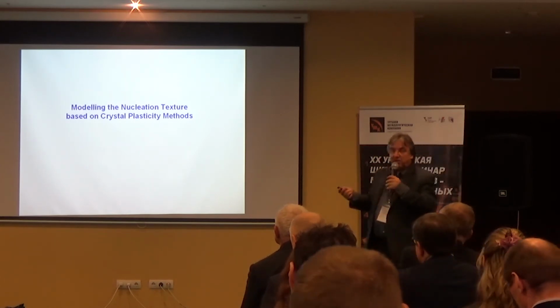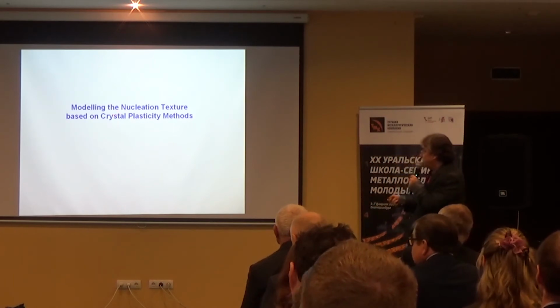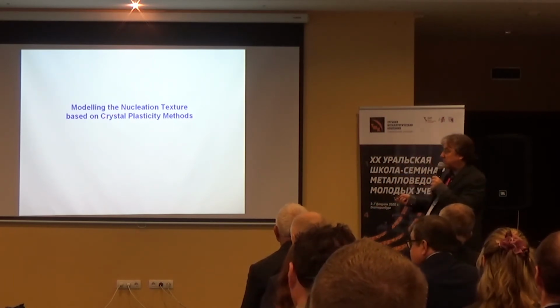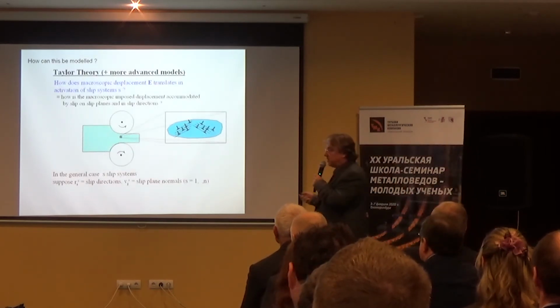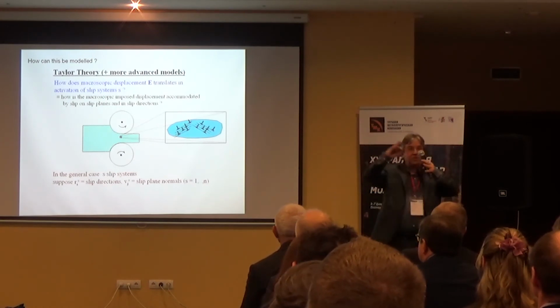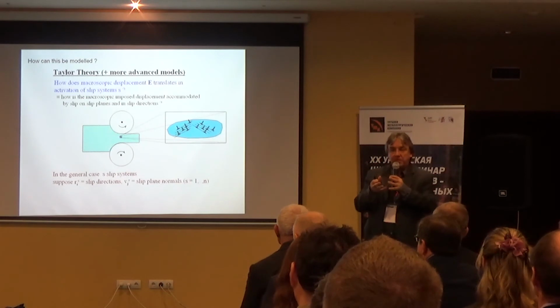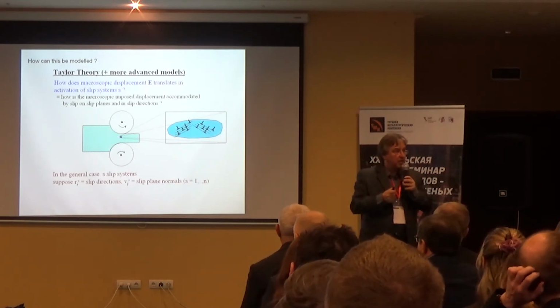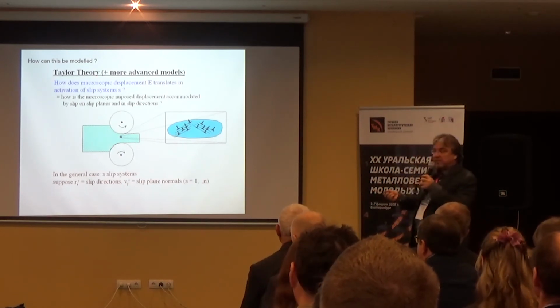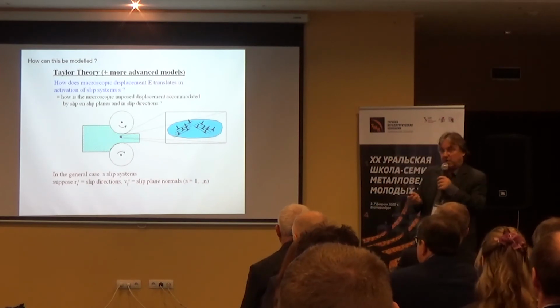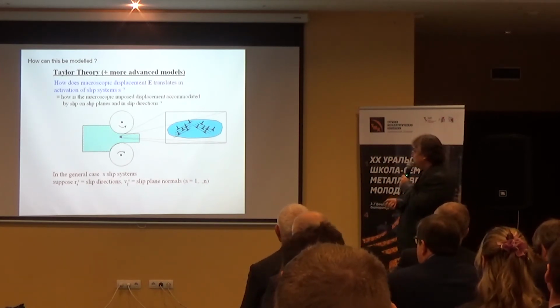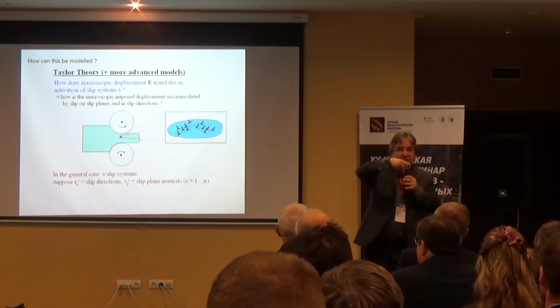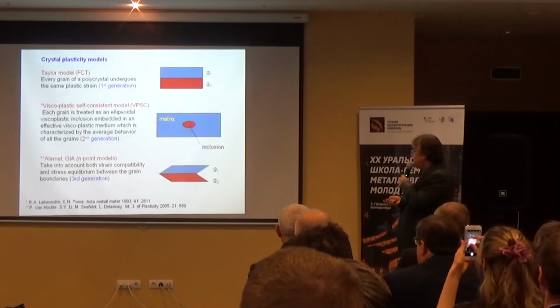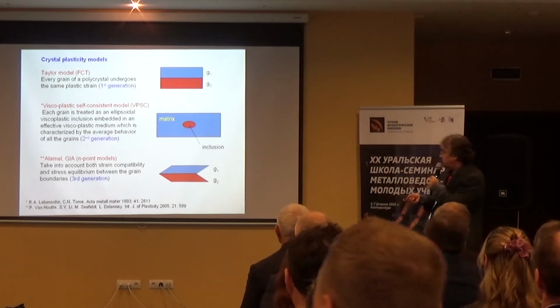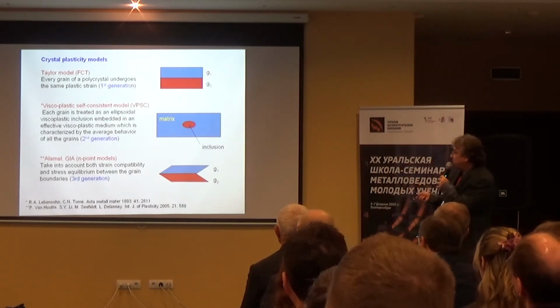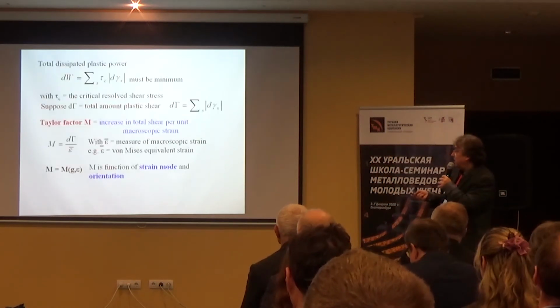Now we can understand the reason why this is, because we can do some modeling based on crystal plasticity methods. What is crystal plasticity? Crystal plasticity will tell you how the macroscopic strain on the level of a workpiece is accommodated by individual crystals in the polycrystalline set. For example, one of the basic theories is the Taylor theory, already from 1938, which allows us to calculate the active slip systems in each of the individual grains. There are various variants of the Taylor theory, and I'm not going to emphasize on this. There are more recent models, but still based on this original idea of Taylor.